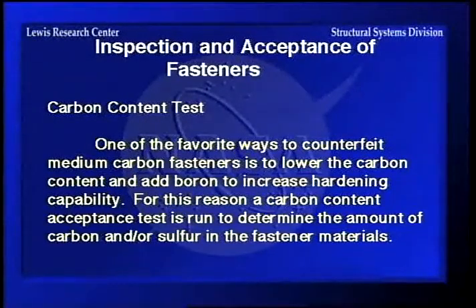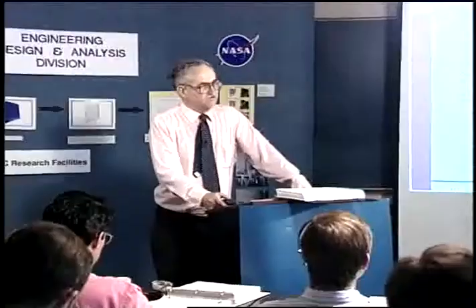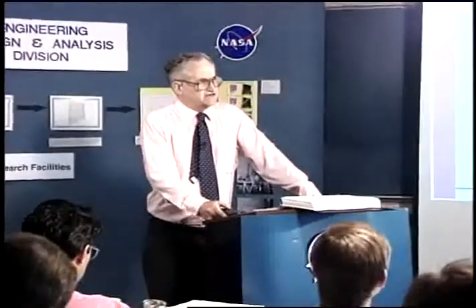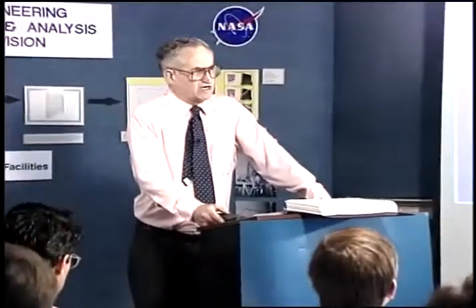most of the time are made by cheating on the carbon content. In order to heat treat a fastener, and we have in the specifications for an alloy steel fastener, it has to be a minimum of 28 points of carbon in order to get heat treating, and usually you use them up around 40. So the counterfeiters can add boron, which increases the hardenability of steel, and boron is cheap and you don't need very much of it to add. So you can take 1020 steel and add a little boron to it and heat treat it.